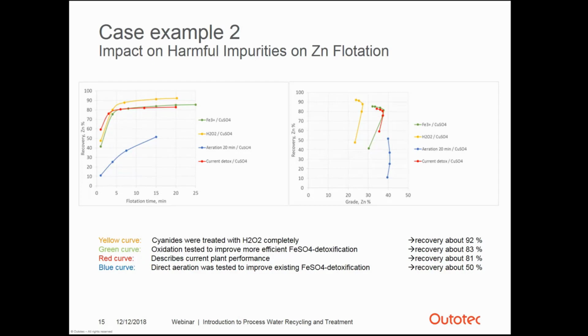So in this study, several flotation tests with different water qualities were performed. The primary focus of the flotation tests was to improve zinc flotation by destroying cyanide. The results of the test work were clear. The current detoxification process doesn't perform well due to the low dosing rate of ferrous sulfate and high operating pH. The method of ferrous sulfate detoxification is recommended to be replaced by a more efficient detoxification.